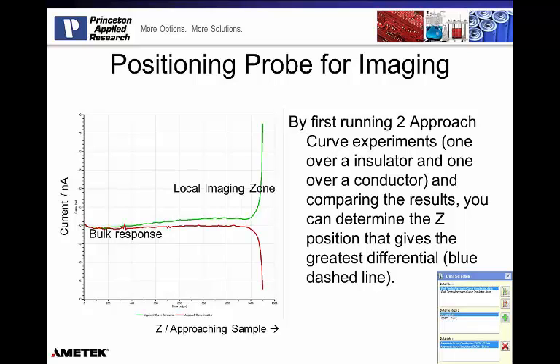Because the Z position shown on the x-axis on this graph goes from 0 to about 1,500 microns. So if I was at the 0 position, so 1,500 microns above the ideal position here, if I took a scan, an area map with the probe at that level and the plane 1,500 microns above the sample surface, what would I see? Well, the response over the insulator and the response over the conductor are the same. So since those electrochemical responses are the same, and since my microscope is based on electrochemistry, I have no way to distinguish where is high activity and where is low activity.